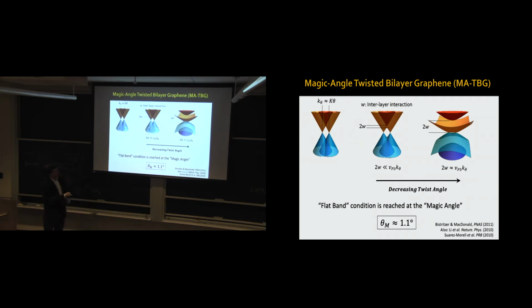There was an earlier paper by Suarez and Morel where they calculated this flat band condition, but they got the angle wrong. MacDonald and Bistritzer got the angle right. There were also scanning tunneling microscopy experiments by the group of Eva Andrei at Rutgers University. It turns out there's a feature in the spectroscopy of graphene associated with this gap, a Van Hove singularity, and they saw that its energy went to 0 at about this angle. So there were already hints that something funny was happening electronically at this angle.